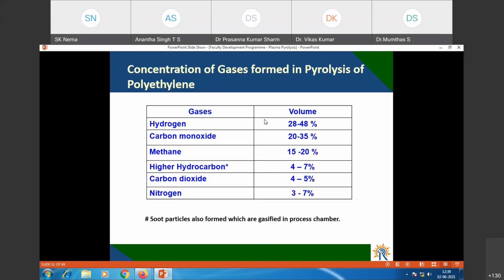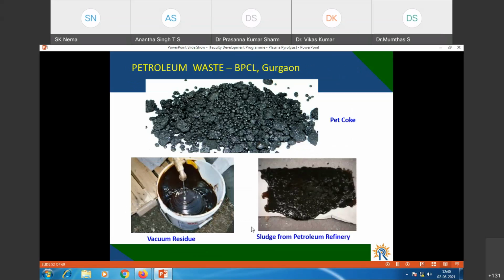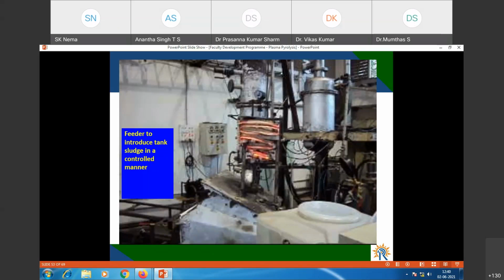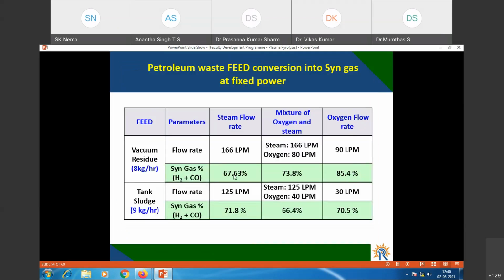You can see gases which were formed from the pyrolysis. Simple polyethylene was pyrolyzed, so we got about 28 to 48% hydrogen, carbon monoxide and methane, 15 to 20% methane we could obtain, and some higher hydrocarbons and other things were there. These various petroleum products we could pyrolyze, and we could generate carbon monoxide, and this gasification was done for these different petroleum products, petcoke, vacuum residue and sludge, and we could demonstrate the carbon monoxide and hydrogen formation from these, and vacuum residue has given us the highest amount of hydrogen and CO syngas. This was the system which was used, and you can see here from vacuum residue we got about 85.4% of syngas, and that was the highest.